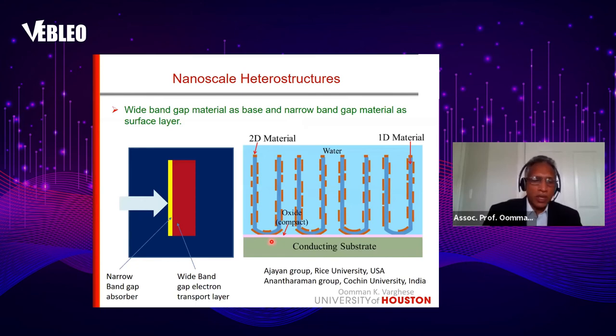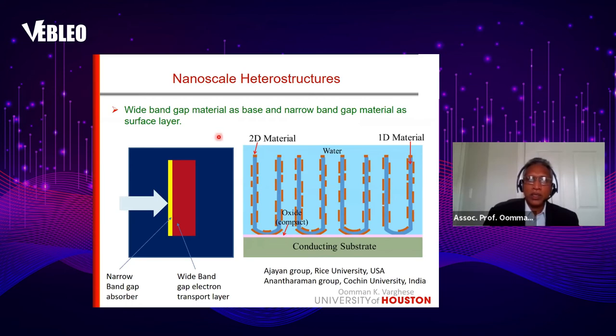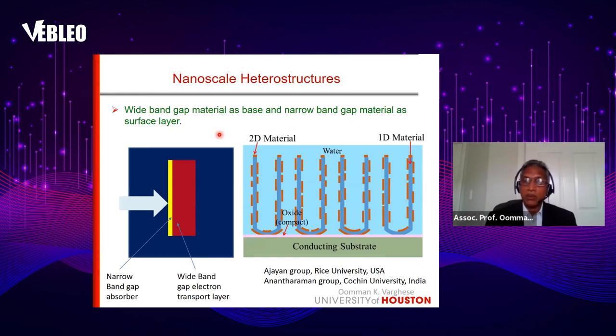The challenge with using a single band gap material is that wide band gap materials don't absorb light across a broad solar energy range — though they are stable. Narrow band gap materials can absorb light over a wider energy range, but they may not be stable. What we did was combine 2D and 1D materials to address this issue and make a combination of wide band gap and narrow band gap materials to find a solution.